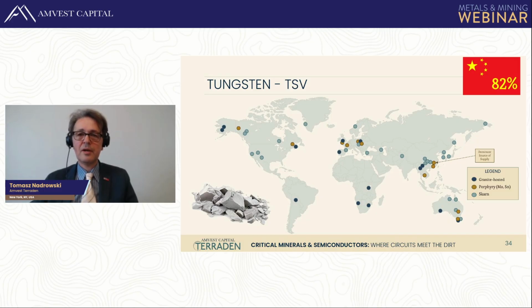As we hear that China is the Saudi Arabia of rare earths, it's also the Saudi Arabia of tungsten, because you find tungsten-tin greisen, so hydrothermally altered granites in China. You find there skarns with tungsten, you find porphyries. So as you see, there's a lot of concentration of tungsten, but tungsten can be found also elsewhere. There's a new mine being built in South Korea at the moment, and there is also production in Bolivia, Myanmar, and it's possible also to develop projects in North America. It's a very interesting metal because at the same time it's highly conductive, but its atoms are not easily dislodged because of a strong metallic bonding that tungsten benefits from.